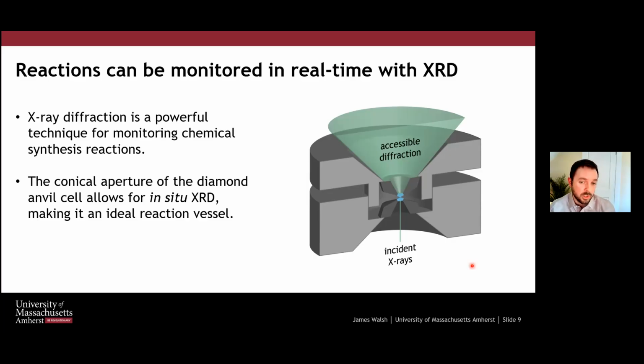So usually we use X-ray diffraction in solid state chemistry after we've done the synthesis. So you spend a few days doing the synthesis, and then you take the crystals that hopefully form, and then you do the analysis and you try and figure out what you made. With the diamond anvil cell, we're able to do in situ X-ray diffraction, monitor the reaction in real time. And that's extraordinarily powerful. And so the diffraction that we're able to access is because of this conical aperture in the diamond anvil cell. And so we're at the stage where we have this 80-degree conical aperture is more than enough to do what we need to do, especially with the high energy of the synchrotron sources.